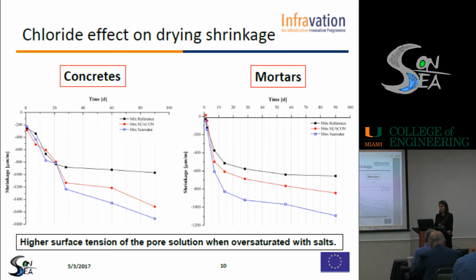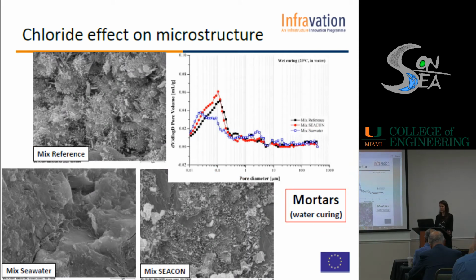We decided also to have some information about the microstructure to better understand this behavior, and so we considered two different techniques, the SEM and the MIP, to understand the microstructure and the distribution of the pores inside the material. So we produced the same mortars that I told you before, so mixed reference, mixed seawater, and mixed SEACON, and we stored them first in water for all the time that we performed the investigation.